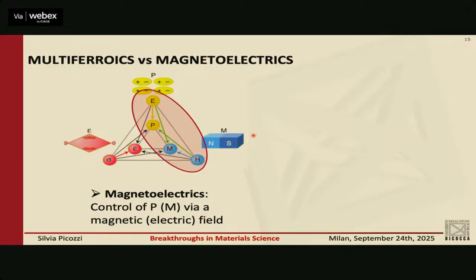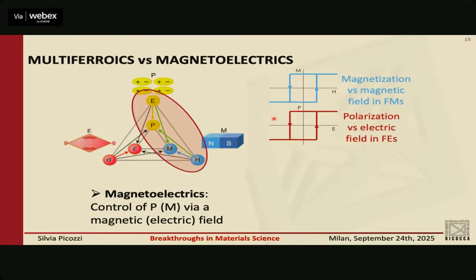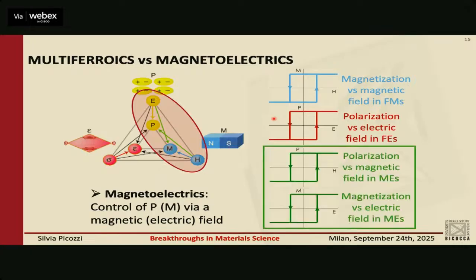Multiferroics are materials that have a spontaneous magnetization and a polarization. Whereas a magnetoelectric is a material in which you control ferroelectric polarization with a magnetic field, or magnetization with an electric field. So in addition to having, in a standard magnet, an M-H hysteresis cycle, or a P-E hysteresis cycle in a ferroelectric, in a magnetoelectric you have a kind of crossed hysteresis cycle, so you have P versus H or M versus E. So a magnetoelectric is something in which you can control one property with the non-conjugate field.